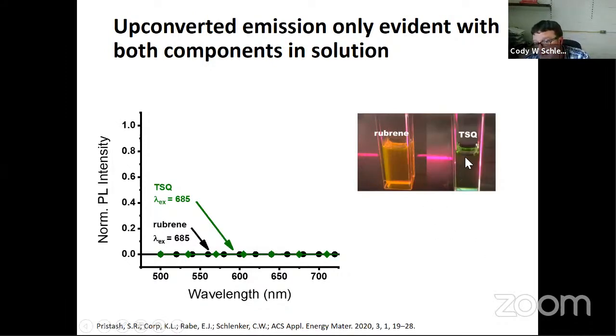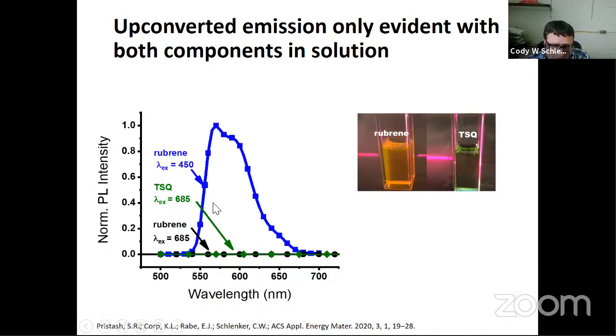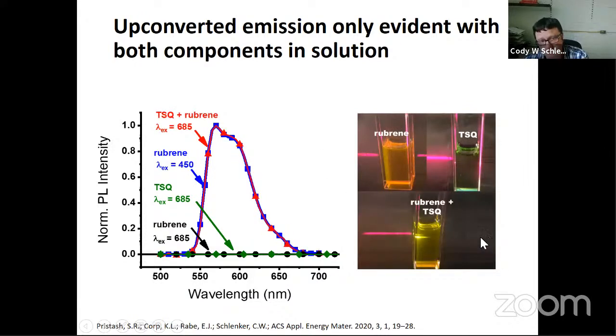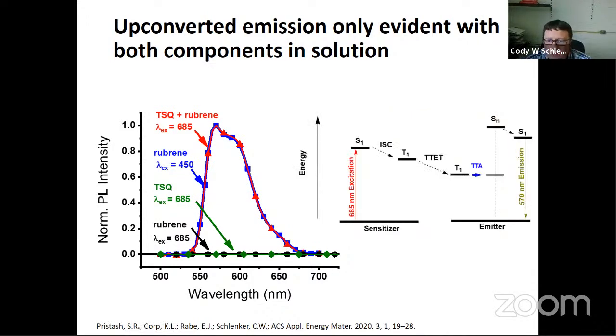If we excite our dye by itself in the red region, we see no emission as well. Here is the emission from the rubrene if we excite it into its absorption. We see 450 luminescence. If we take the mixture of our two materials together, we now see what used to be dark in both cases. Red excitation of each of these individual components by themselves leads to no fluorescence. We mix them together and we now see the upconverted fluorescence from the rubrene, with no platinum, iridium, rhodium, rubidium, anything like that around. Okay, so this is essentially the process that we're looking at here.